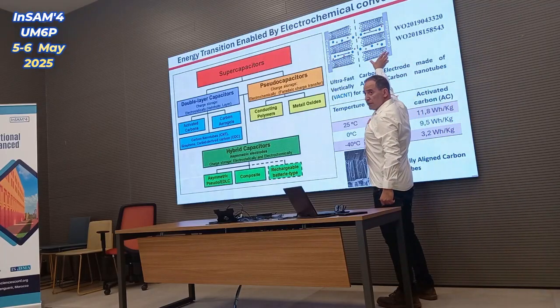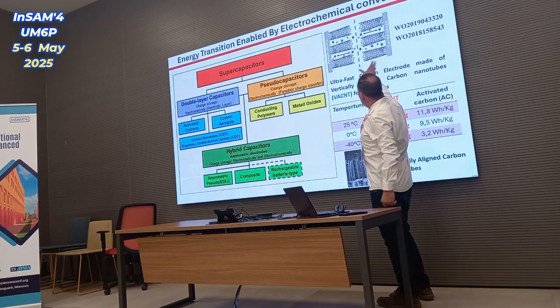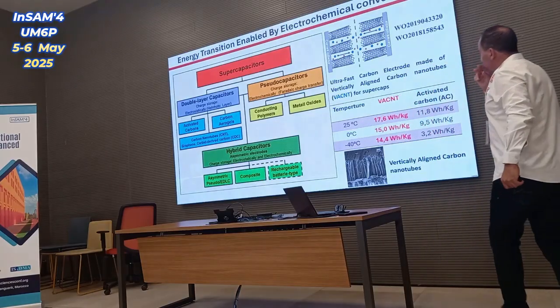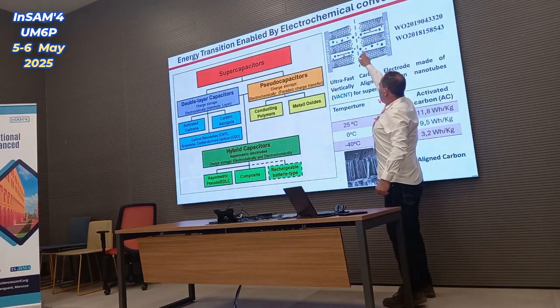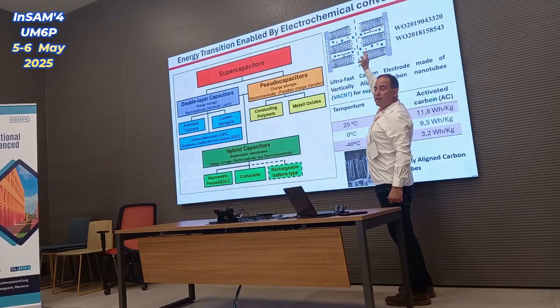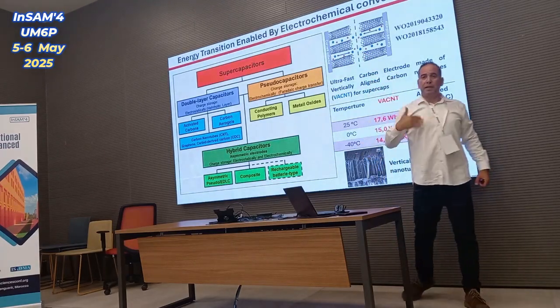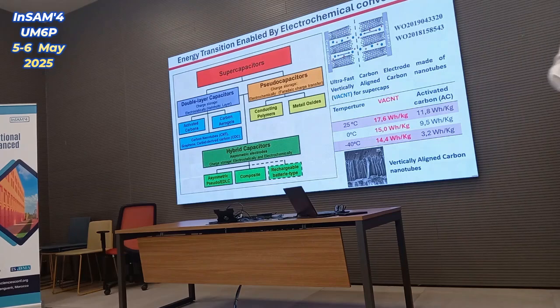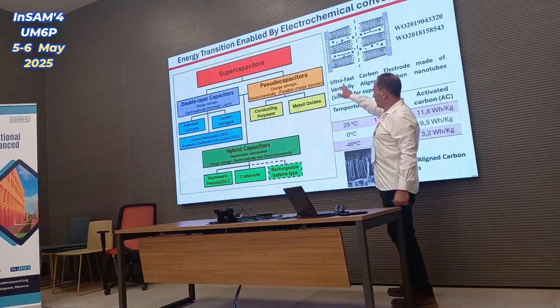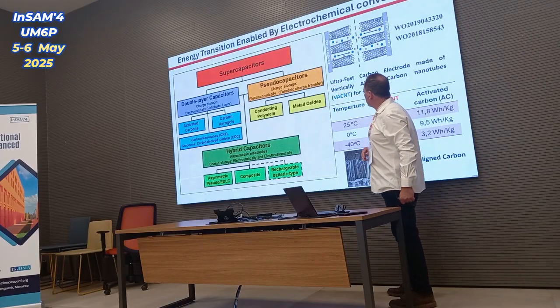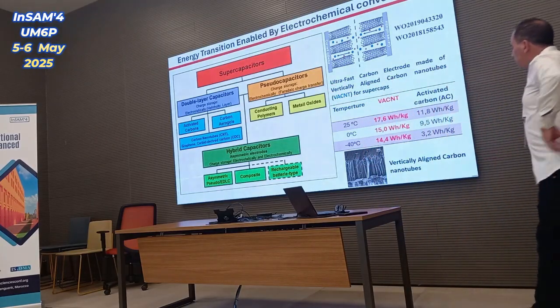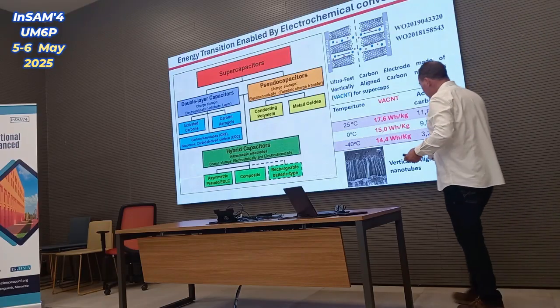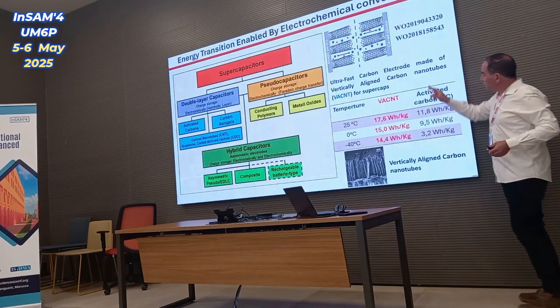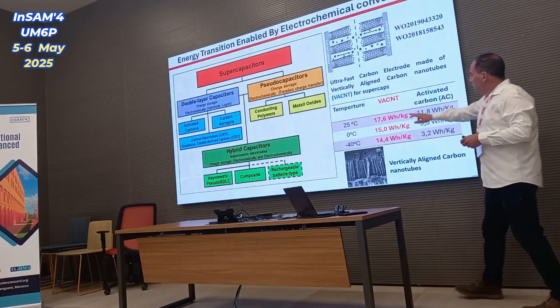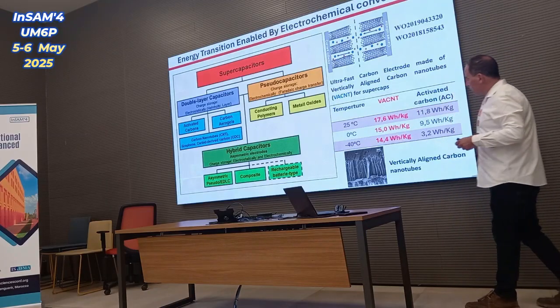And the thickness of the layer of the nanotube is 100 micrometer. This configuration allows fast transport of the ions between the channels of the nanotube, then providing very high power and high speed in charge and discharge. This is why we have called this system ultra-fast supercapacitor. And here is an example of performances using this vertically aligned carbon nanotube material for supercapacitors.